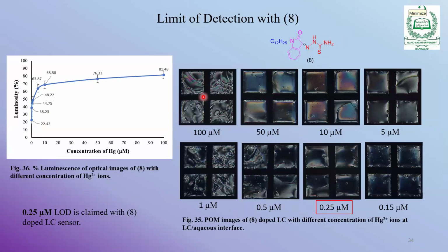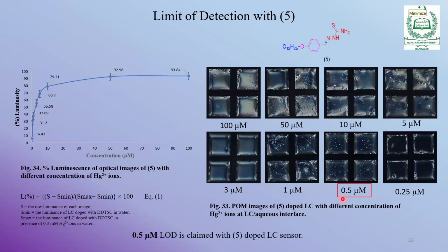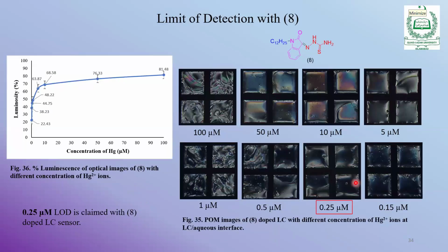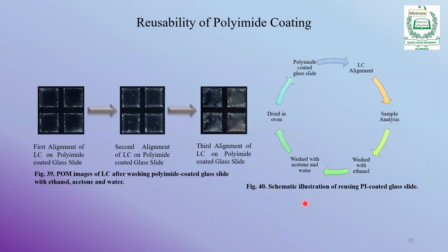With the second one, you see again from 100 micromolar going down to 0.15 micromolar. This is the luminosity curve, decreasing down, and you see that at 0.25 micromolar you get some luminosity above 30%. So this is the limit of detection for amphiphilic ligand 8, and for the previous one it was 0.5. So from here also you can see that this one is the most suitable compared to the first one.